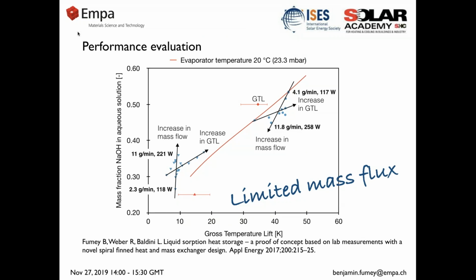And here are now some of the performance, or the performance we reached with our setup, here again shown in this gross temperature lift and mass fraction mapping. And red here now the equilibrium line at 20 degrees. At the moment, I show this equilibrium line because these tests were done at a condensing and evaporating temperature of 20 degrees, which I must state now, as we saw previously from the realistic temperatures, is of course not quite fitting.